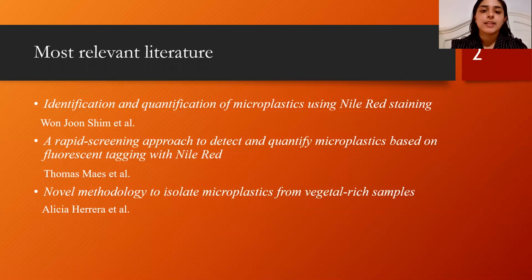This was actually the journal that inspired my idea of using fluorescence spectroscopy for potentially identifying the concentration of microplastics in solution. This journal also proposed an ideal excitation wavelength range when identifying what dyed microplastics should look like in solution. This range was between 450 to 510 nanometers, which I will reference later, but did allow me to identify and discriminate between what is a dyed microplastic and what is not.